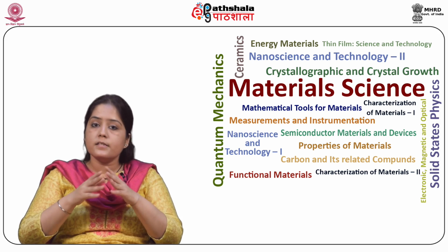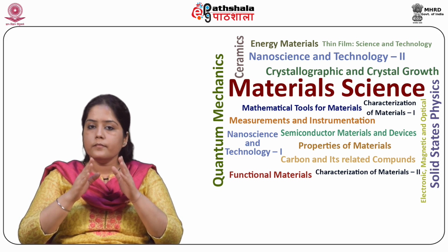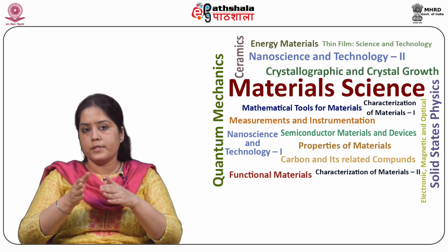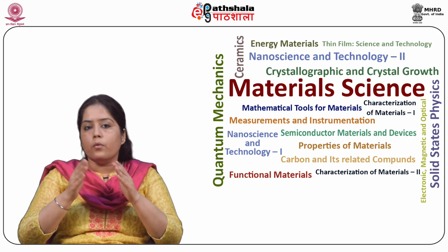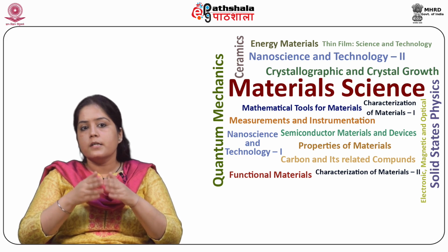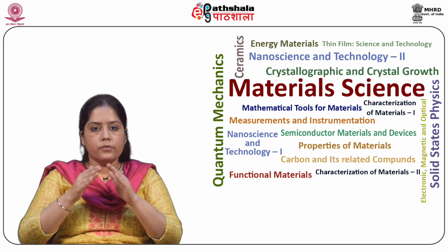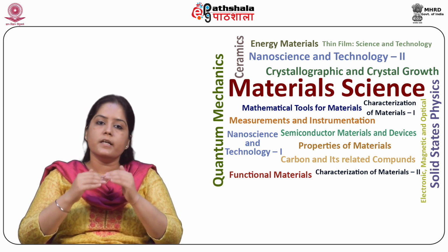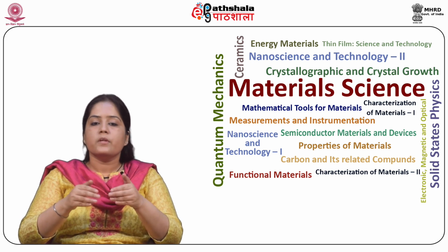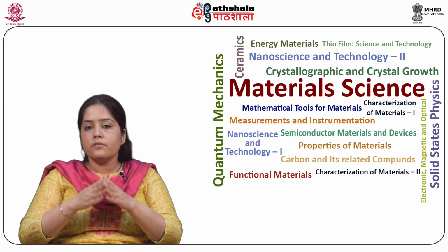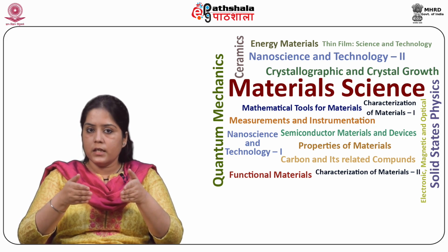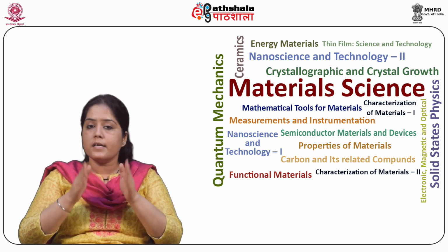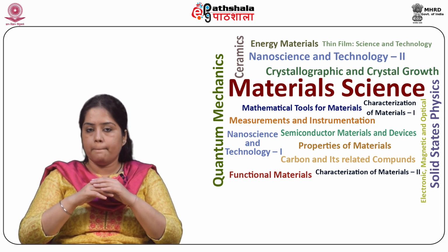During the acid treatment, surface functional groups such as COOH and C=O were formed on the electrode surface, which was found to significantly increase the chemical activity in highly acidic media.